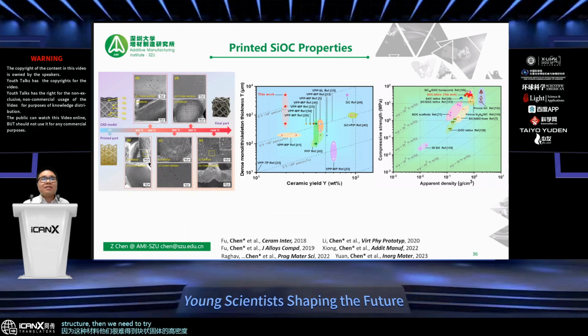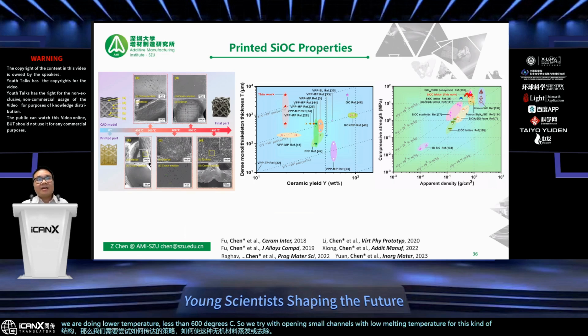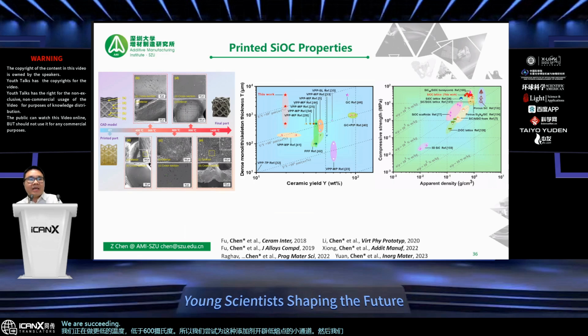Then we need to try a strategy for how we can make the evaporation or removal of this kind of inorganic and organic material happen at lower temperature, less than 600 degrees C. So we try opening small channels with a low melting temperature for this kind of additive. Then we succeeded in making small channels before the overall evaporation and removal of the rest of the organic components. So there will be no cracking, and not much shrinkage. The shrinkage is much more uniform, and the cracking is eliminated.